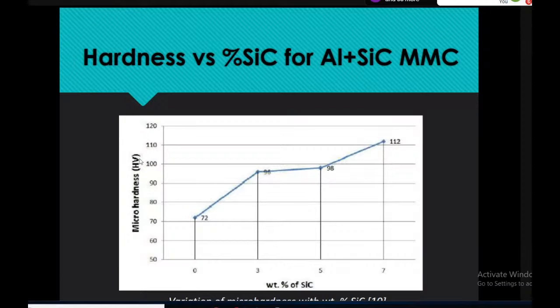Now just see the micro hardness, it is in HV, Vickers hardness. It is 72 initially when 0% SiC is there, but as you add 3% silicon carbide powder, the hardness could improve. This is for the aluminum material. If you add 5%, it could go up to 98. And if you add 7%, it may go up to 112 Vickers hardness.